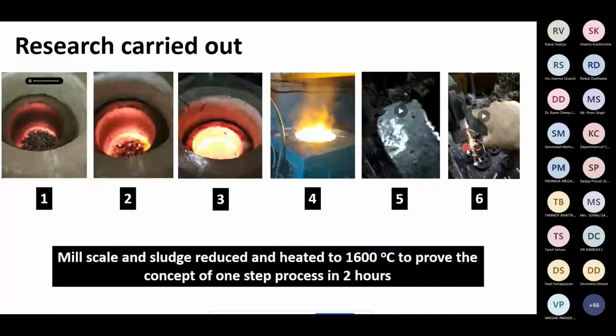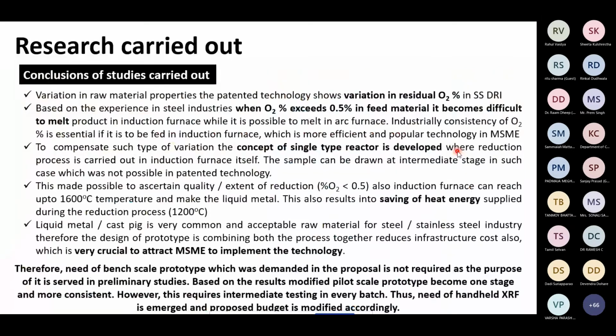We have even taken out XRF and XRD analysis. It also gives good, promising results. So the research study which we carried out provides very promising results. Conclusion of our study: with variation of the raw material properties, the patented technology shows variation in the residual oxygen in a direct reduced iron.